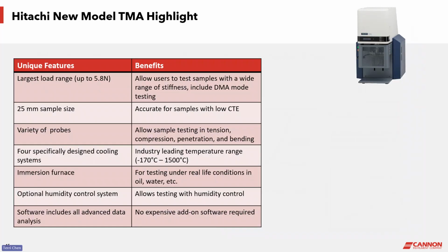Hitachi TMA provides users with the highest force range, up to 5.8 Newton. This benefits testing large and stiffer samples and is also good for DMA mode testing. In addition to high force, this instrument also allows large sample sizes, which provides the best sensitivity for testing samples with low CTEs.